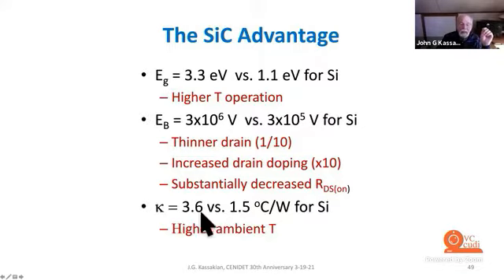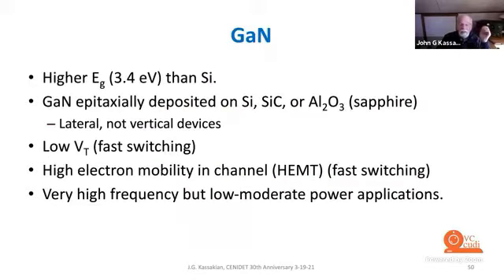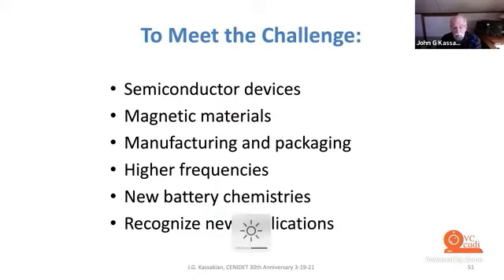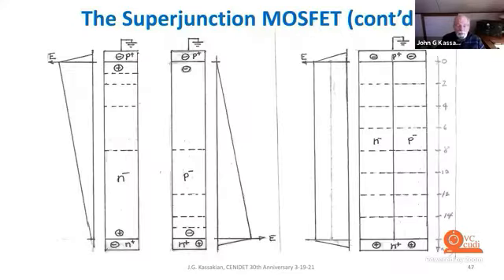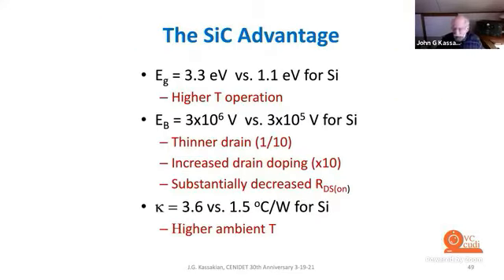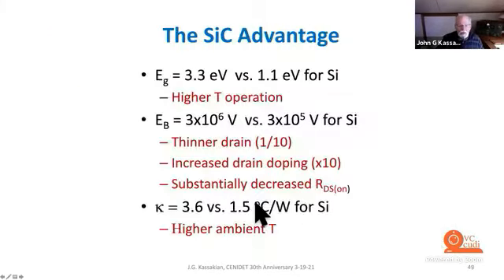In addition, with a thermal coefficient of conductance of 3.6 versus 1.5, we can operate a silicon carbide device in a much higher ambient temperature.